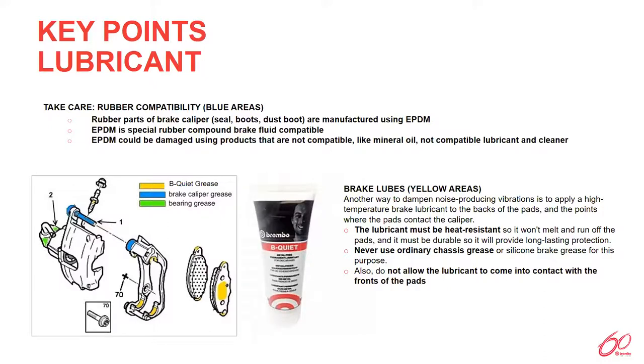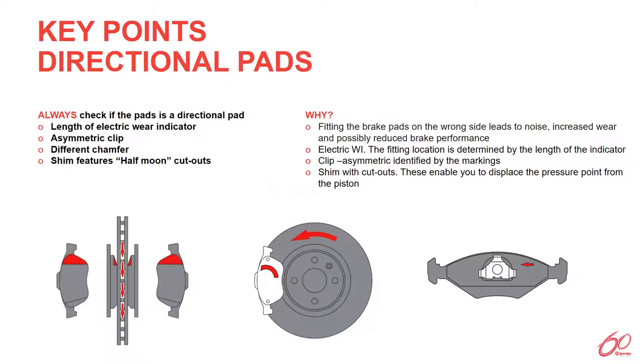And in a brake system, there are several contact points that will need to be treated as part of the repair process to ensure free movement. The old school habit within the industry that uses copper grease as the universal lubricant is again a no-no, as within the braking environment it can result in galvanic corrosion that is further worsened by the contamination of acidic cleaners due to the owner's desires of keeping the alloys or their rims sparkling clean. So the exposed contact points require a washproof lubricant, usually one of petroleum base, like our Brembo B-Quiet grease.